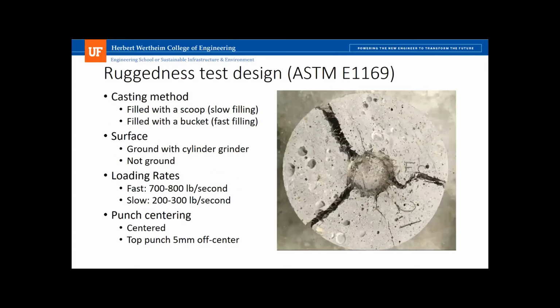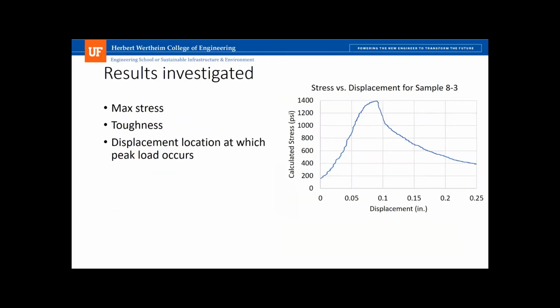So our ruggedness test, we looked at the casting method, filling it with a scoop versus filling it with a bucket very fast. We looked at grinding the samples versus not ground. We did fast versus slow loading rates. You're talking about 2 to 4 times loading rate, and a 5 millimeter off center of your punch. So we controlled all of these variables in a testing matrix specified in ASTM E1169 to see if these factors were statistically significant. And we looked at, with our test, the max stress. We looked at the toughness, or the area under your displacement calculated stress curve, and we looked at the displacement location at which the peak load occurs.